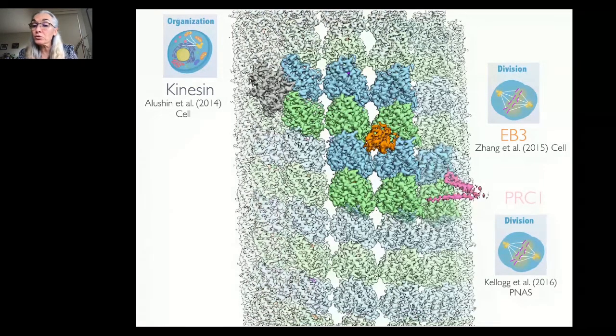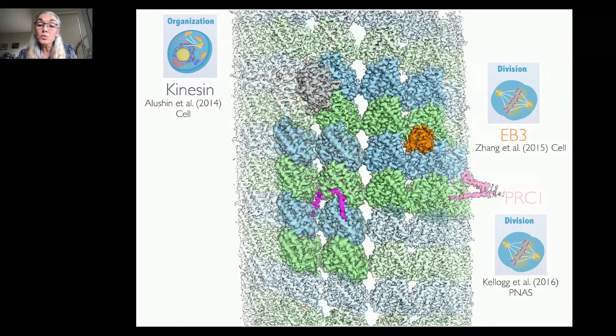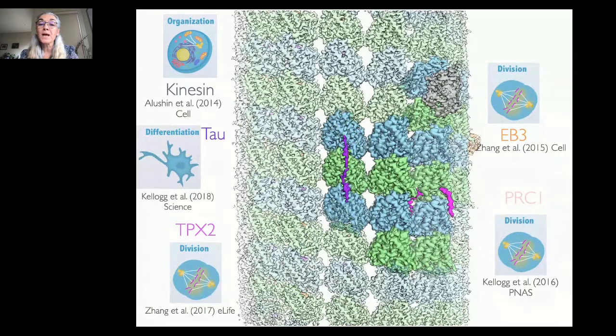We studied the structural MAP PRC1, which actually cross-links microtubules. We've also studied TPX2, which is a microtubule assembly factor, very important to establish the mitotic spindle, and neuronal MAPs like tau, which act to both stabilize and also organize microtubules in axons. And when it misbehaves, it detaches from microtubules and can form amyloid bundles and give rise to neuropathies like Alzheimer's. So in cases like this, there are structures for which there are crystal structures that we can then try to dock into the density, to see whether they change in conformation upon binding to microtubules.